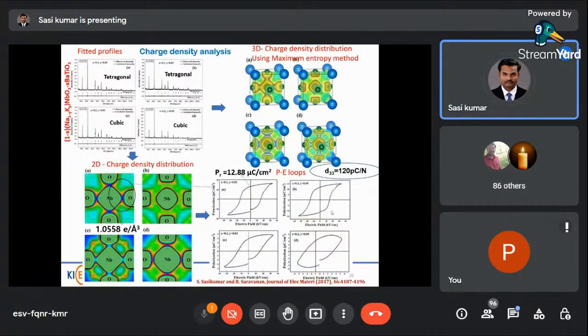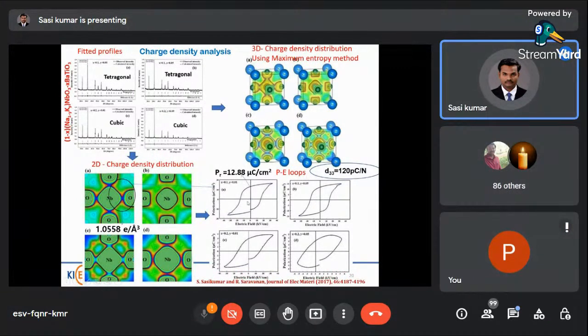And then another interpretation from the powder XRD analysis is charge density analysis. The powder XRD data is subjected to Rietveld refinement, and then charge density analysis using the maximum entropy method. Here is the three-dimensional structure for the tetragonal structure, and then the two-dimensional charge density on the 001 plane.